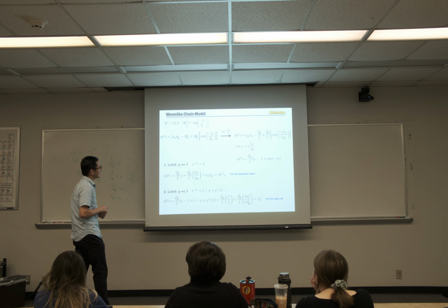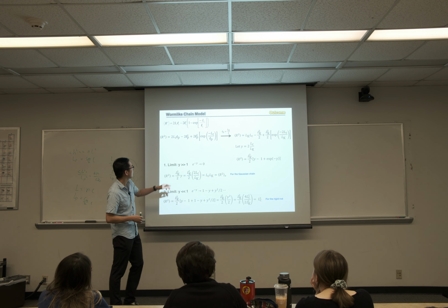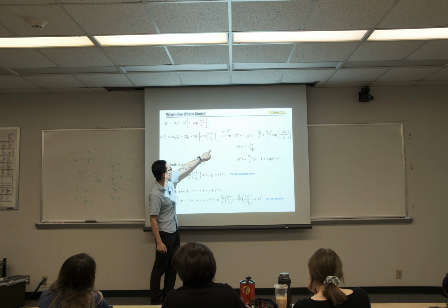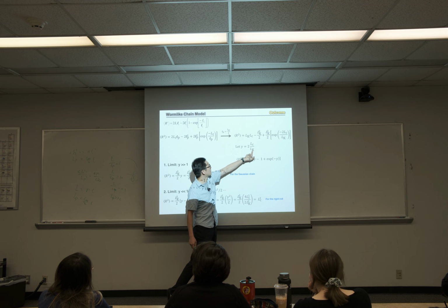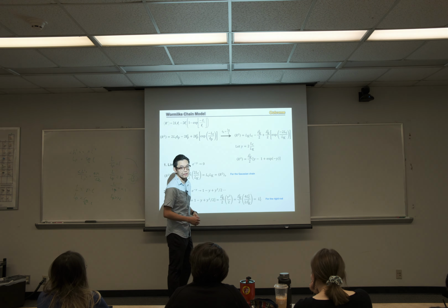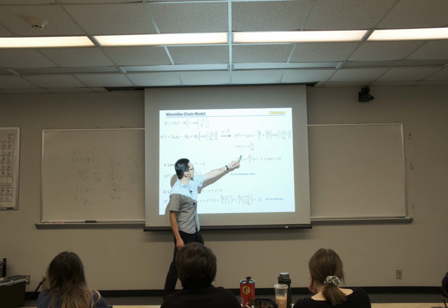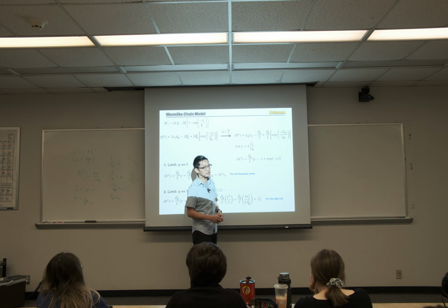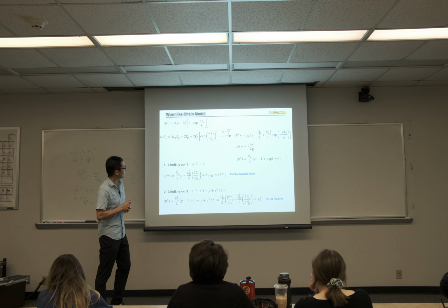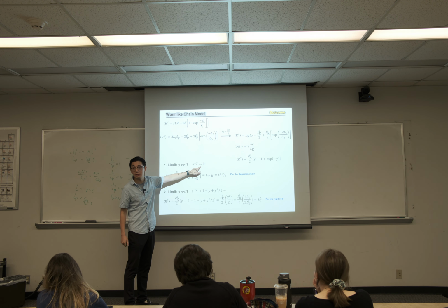Right, like we had. So let's talk about two extremes. What are two extremes? One extreme is when y, in this case y is defined as 2LC divided by LK, contour length over Kuhn segment. You can imagine when y is much bigger than 1, this basically means your contour length is much bigger than persistence length. That's the extreme of flexible coil. In the extreme of flexible coil, exponent e to the minus y will be closer to 0.